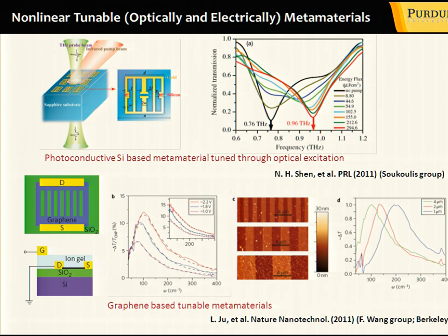Yet another way to control properties of your metamaterial is through nonlinear response, either optically or electrically. That work comes from Costas Soukoulis's group. He uses this structure which has photoconductive silicon, and when you irradiate it with light, you induce charge carriers and it becomes conductive, and there is a shift from this low frequency mode to the high frequency mode. Basically, when you irradiate it with light, you shift from this resonance to this one, which you could, of course, detect by using a pump-probe experiment. So in this case, you have the electric permittivity, which depends on intensity. So this is a nonlinear way to control the response of metamaterials.